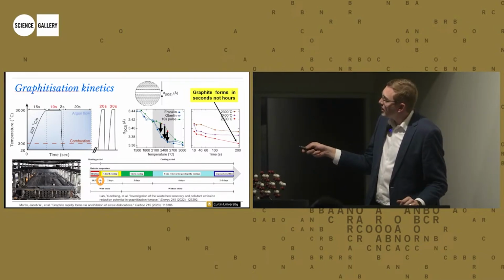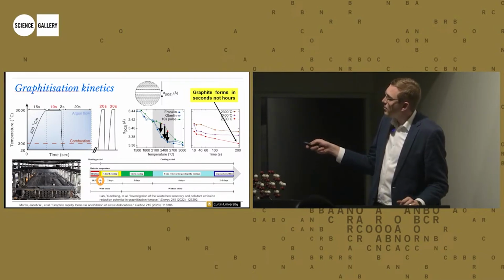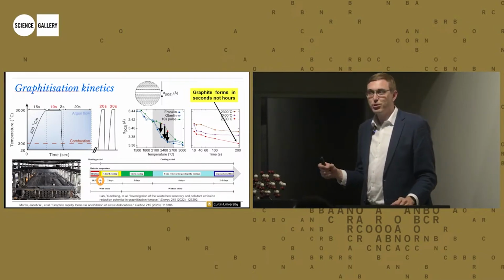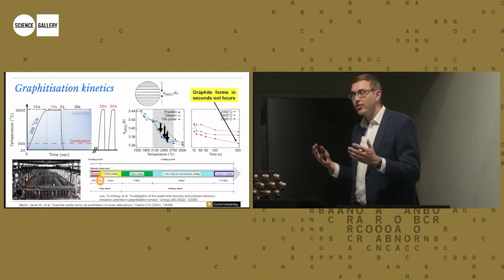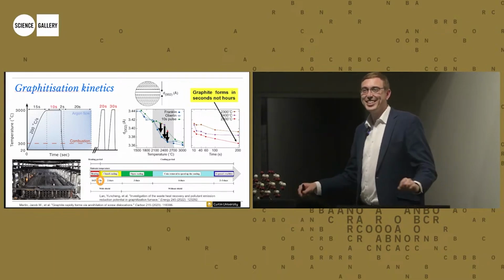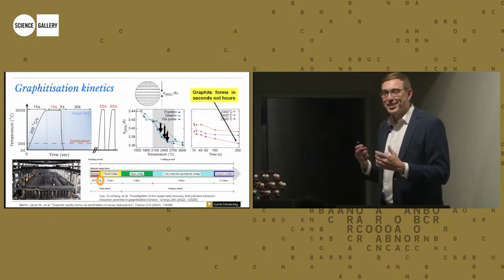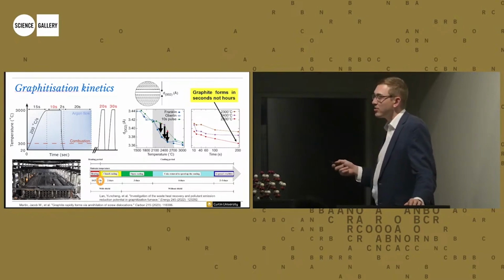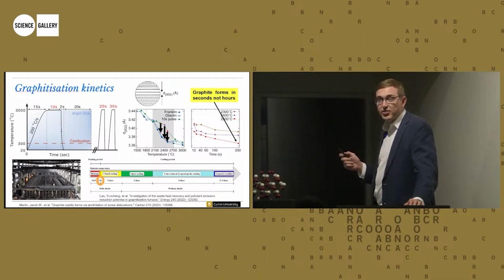And because the kinetics were incorrect, this was modeled as a first order process, but it's actually a second order process. Some companies knew that they didn't need to cook for so long, but some other companies, I think this was news for them. So graphite forms in seconds, not hours.